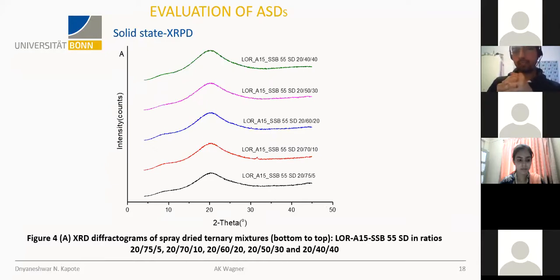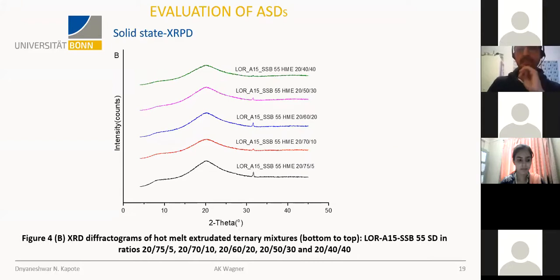While in the case of the amorphous solid dispersions for the ternary mixtures, we can clearly observe that all the ternary mixtures were completely converted into amorphous form, with a halo pattern and no intense peak. The same observation was made with our hot melt extrudeds, in which all the samples were completely amorphous in nature.